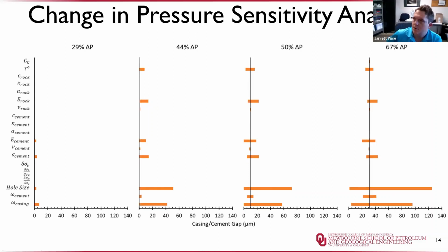Finally, if we reduce the pressure down to 67%, which is, I believe, hydrostatic pressure for this well. So basically the well is completely depleted and just has a water column in the well. You can see that the base case has a 30 micron microannuli size, but if you have a huge hole size, you can get up to about 130 microns, or if you have a thin casing, you can get up to almost 100 microns.